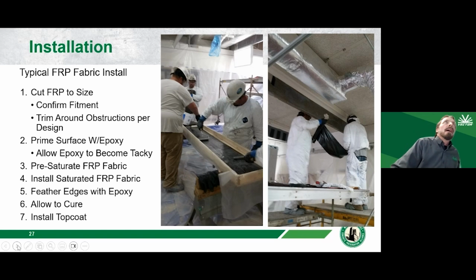So a typical installation is to cut the FRP to size. FRP typically comes in a 300-foot roll, depending on the type of FRP, but we want to put the largest pieces up possible. We don't want to splice if we don't have to. If we do overlap, the FRP designer will provide what that development length or overlap length will need to be between two different pieces. But the objective always is to try to put the biggest pieces up possible.